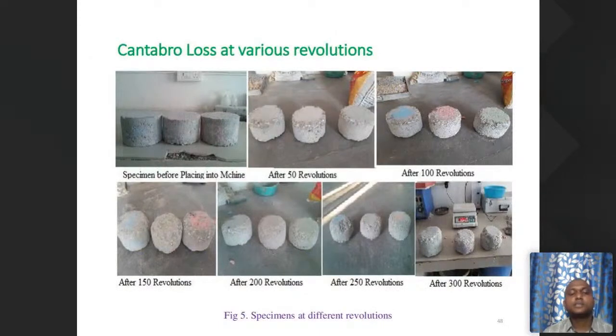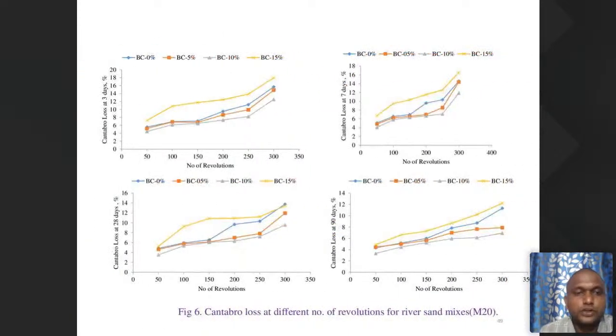Yeah, these are the specimens before placing into the machine, in the Los Angeles equipment. Here is how the specimen looks after 50 revolutions, after 100 revolutions, after 150, 200, 250, and 300. That is enough as per the ASTM. So these are the tests we did, with the number of revolutions from 0 to 350, that is from 50 up to, in most cases, 300.